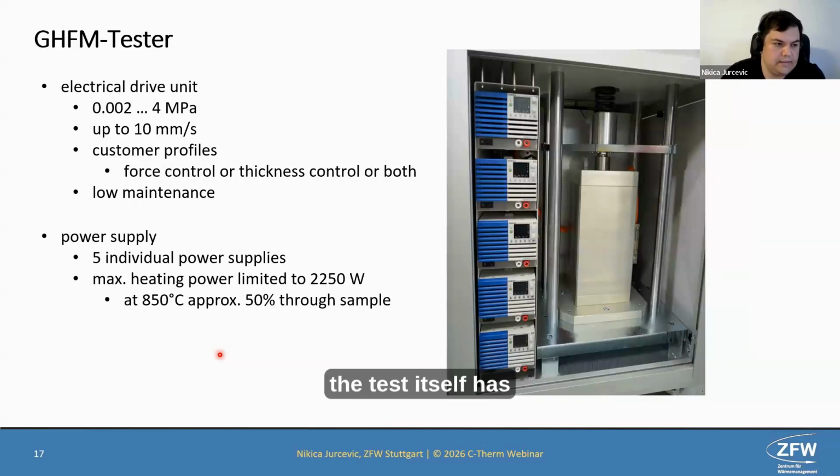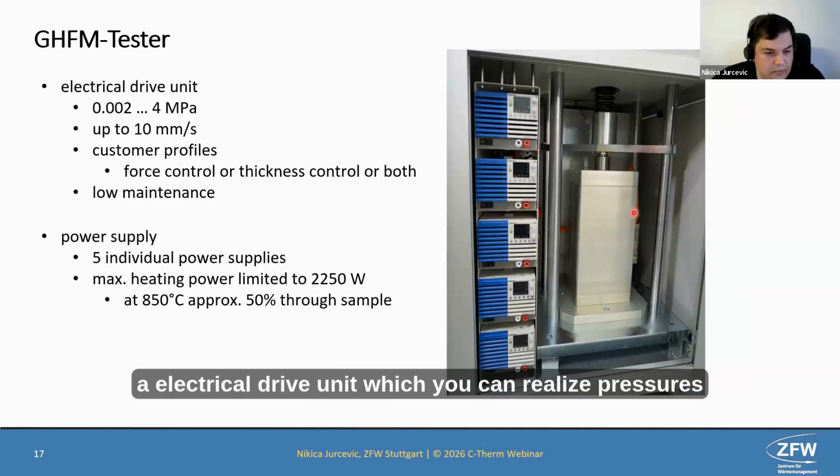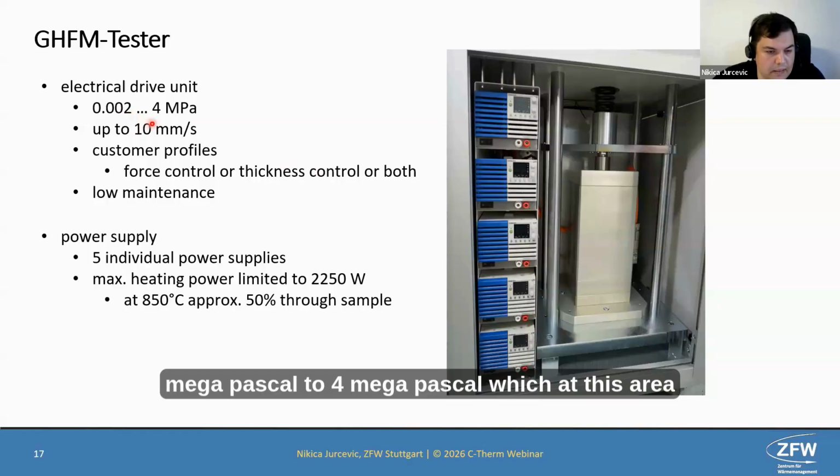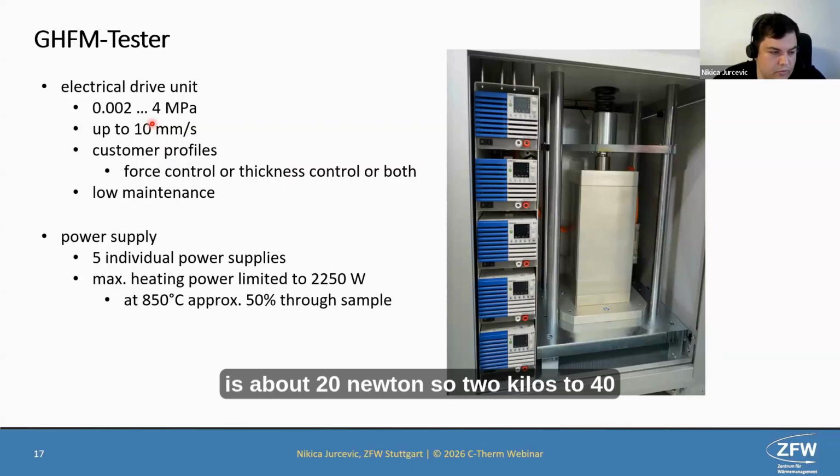Then the test itself has an electrical drive unit, with which you can realize pressures from 0.002 megapascal to 4 megapascal, which at this area is about 20 newtons, so 2 kilos, to 40,000 newtons, which is 4 tons.